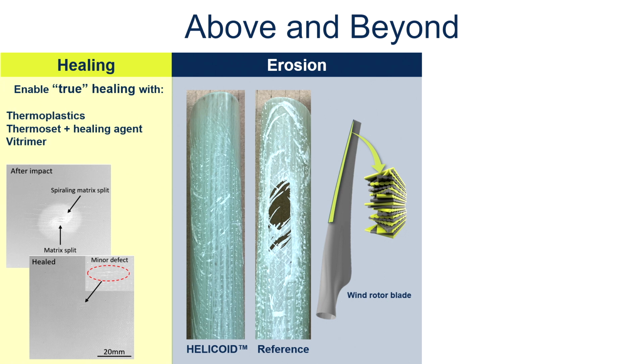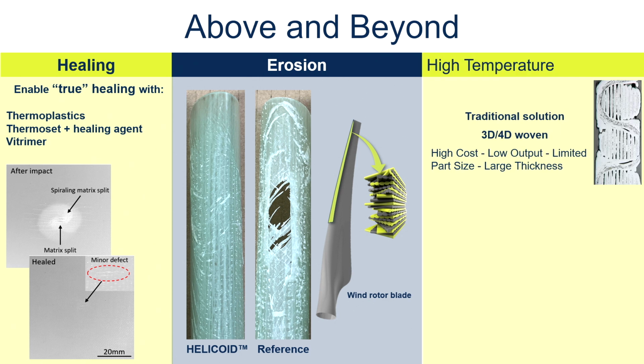We have an interesting application in erosion, a key issue for wind rotor blades. After a while, especially offshore wind blades, they tend to suffer from rain erosion. It causes the damage that you see in the reference material. The erosion is so harsh that it breaks through the entire structure of the blade. So it's no more a problem of aerodynamic efficiency, it becomes a problem of structural efficiency. You need to stop the blade, and that's a huge cost for maintenance. And on the left, it's what we are able to do with our tech.